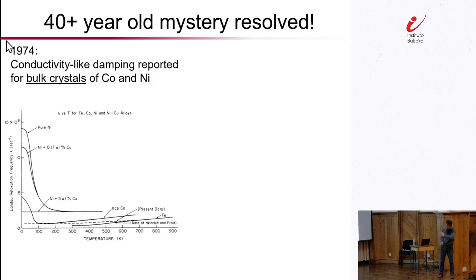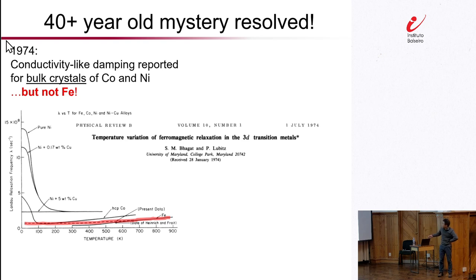Okay, so this is really one of the last things I will talk about. This is another historical context behind our experiment. It turns out that back in the 1970s, there were already some people who studied the temperature dependence of Gilbert damping. Back then they had a different name for it. They called it Landau relaxation frequency, a quantity that's actually proportional to Gilbert damping. So they do see clear signatures of conductivity-like damping, but for some reason, not for iron.